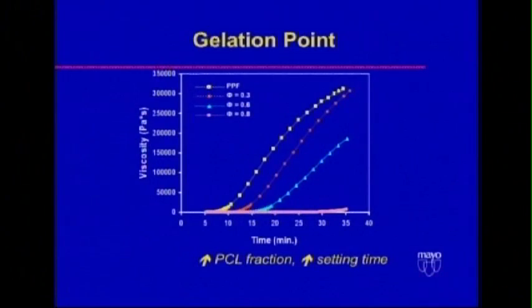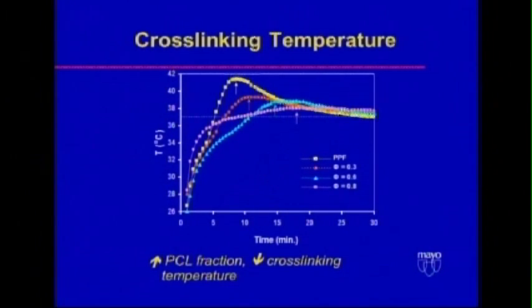So rather than try to teach surgeons new things, we thought, well, let's work on the rheometry of these polymers we're using. And Shanfeng found, as you see, pure polypropylene fumarate is the yellow, and 80% caprolactone is that line down at the bottom, that pink line. And you can change the gelation time, the time at which it becomes cross-linked enough that the molecular weight is infinite and it's just a solid cross-linked mass. You can change that over a wide range by changing the composition. And so change of composition is something that we use, and I'll go into it when I look at the nerve tubes. When the properties aren't good, we can go back and work on composition as one of the things we change to get the properties we want.